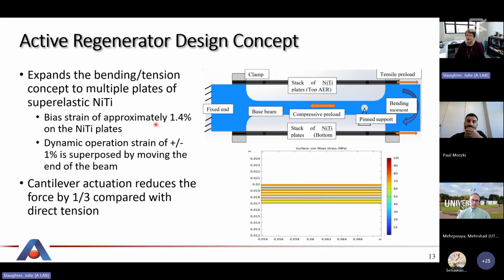So we have a strain of 1.4% that's a bias, and then we're plus or minus 1% on that. And that gives us a temperature change in the material of about, I think, 5 to 6 degrees Kelvin. And that's sufficient to get our ultimate goal of this. And in our finite element model, it said we've got about 1/3 of the force that would be needed for direct tension, so we reduced it by 1/3. So it's 67% of what we would use for that.